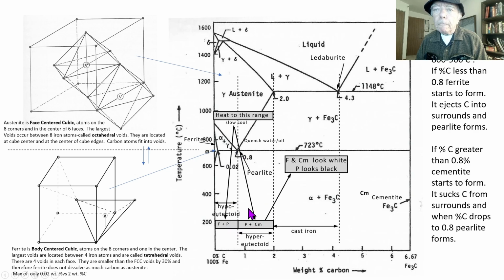Now, over here, above 0.8, sort of the reverse happens. When you cross this line, the stuff that forms is cementite, and it contains a huge amount of carbon. So the region between is depleted in carbon, and it runs down, and you end up with pearlite and cementite. Ferrite and cementite both look white, and pearlite looks black in the optical microscope.